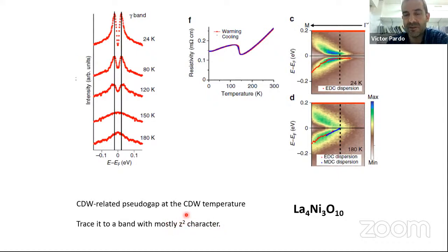And this is interesting because those dz2 bands are the ones that you want to get rid of if you want to move to the physics of the cuprates. So if indeed we get rid of these dz2 bands and put them away from the Fermi level in these nickelates, we could also get rid of these charge density waves that some of these nickelates have and that don't seem to be good for superconductivity.